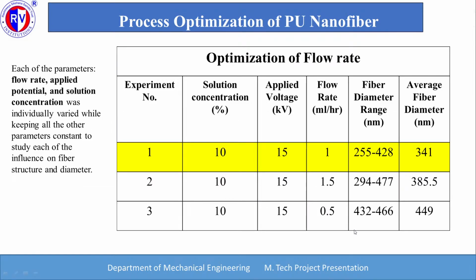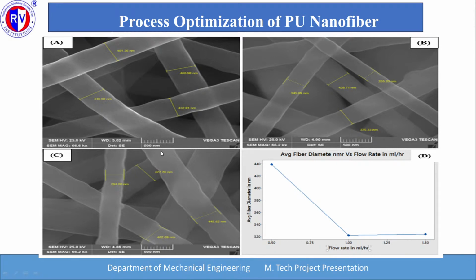Then second, the process optimization of PU nanofiber. Each of the parameters, flow rate, applied potential, and solution concentration, was individually varied while keeping all the other parameters constant to study the influence on fiber structure and diameter. First, optimization of flow rate: the solution concentration and applied voltage are kept constant and the flow rate is changed. We found that a flow rate of 1 ml per hour gives the minimum diameter of the polymer fibers. These are the images we have obtained.